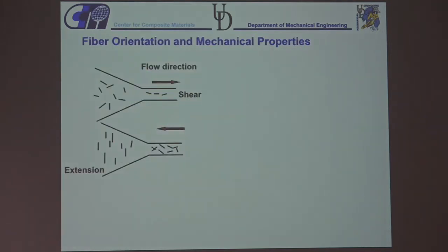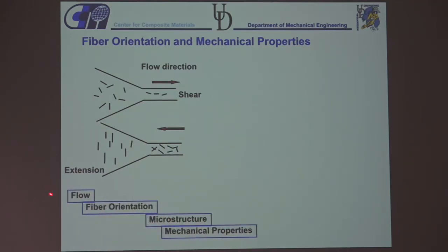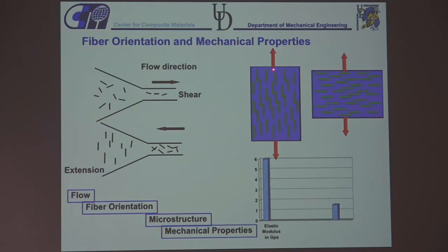Now, one of the problems with that is that here the fibers orient with flow because it goes as a suspension and the fibers can change orientation. And whenever there is flow inside, let's say a shear flow, if you're going this way, injecting it from here, you'll get a lot of fibers aligned in this direction. If you go the other way around, then you have basically extensional flow in this direction because of the divergent section, and you get fibers aligned this way. So by changing the injection location, you have changed the properties of the part. So you have flow that affects the fiber orientation, that affects the microstructure, that affects the mechanical properties. And obviously, if all the fibers are aligned in this direction, you have much better mechanical properties in that direction as compared to the transverse direction. So the direction does play an important role.